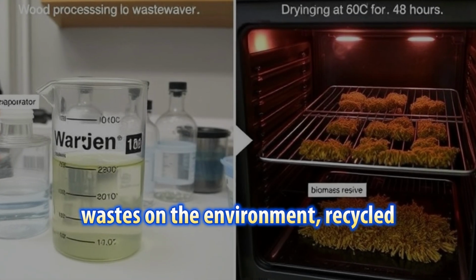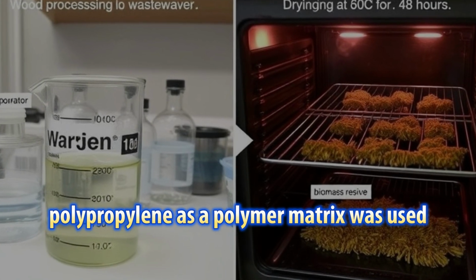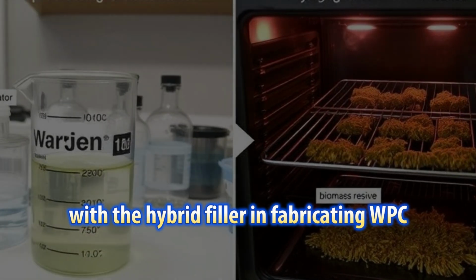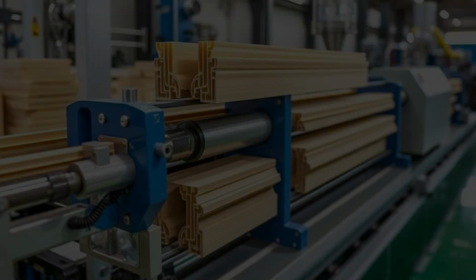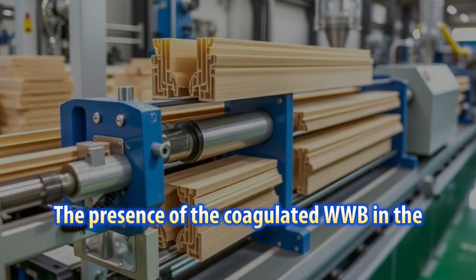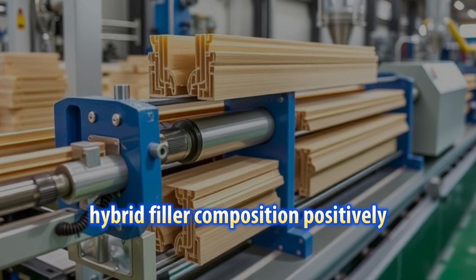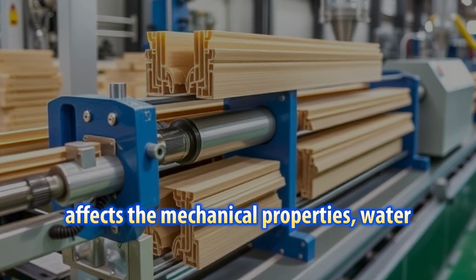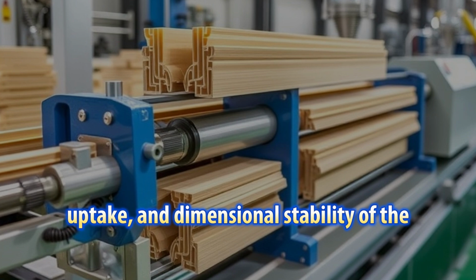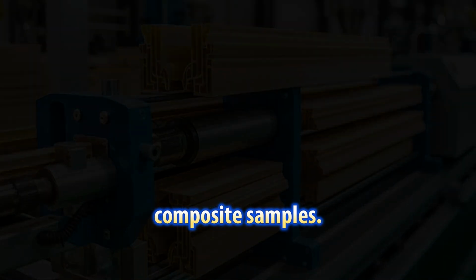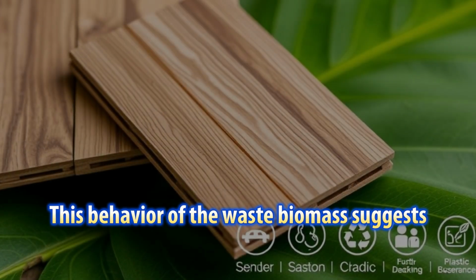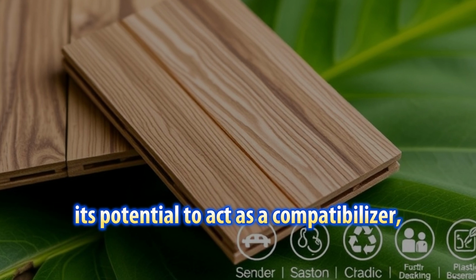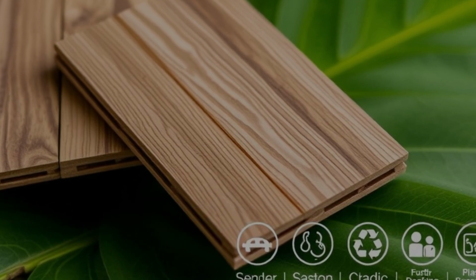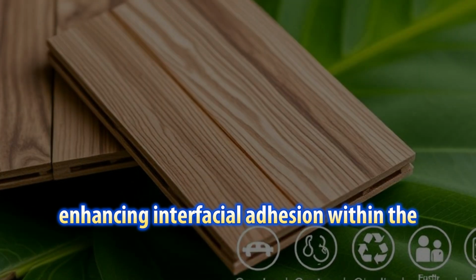To minimize the negative effect of polymer wastes on the environment, recycled polypropylene as a polymer matrix was used with the hybrid filler in fabricating WPC samples. The presence of the coagulated WWB in the hybrid filler composition positively affects the mechanical properties, water uptake, and dimensional stability of the composite samples. This behavior of the waste biomass suggests its potential to act as a compatibilizer, enhancing interfacial adhesion within the composite system.